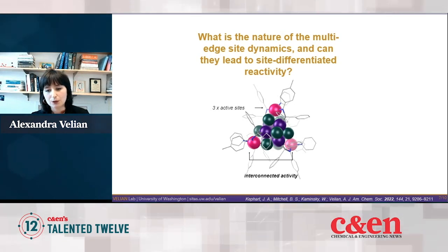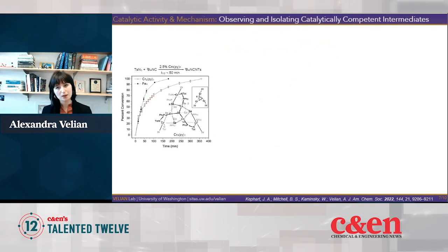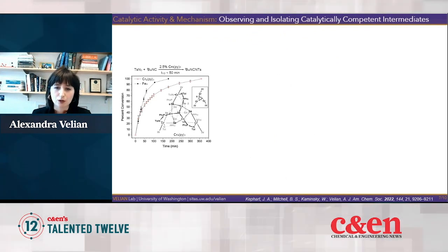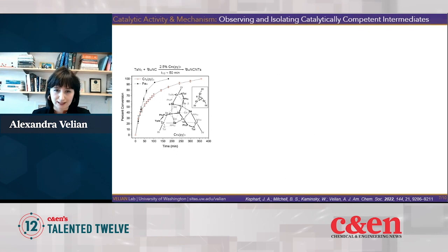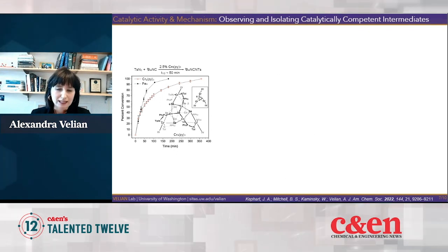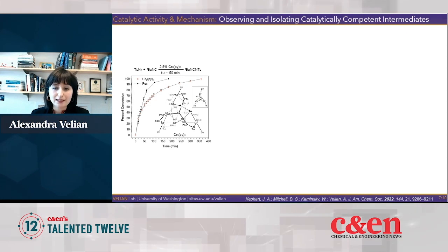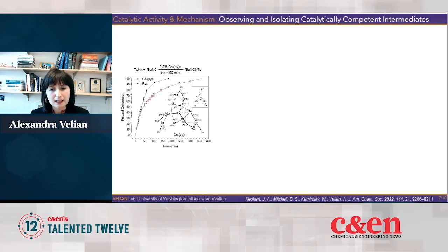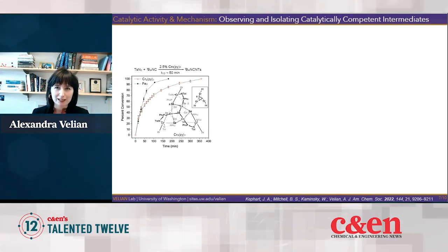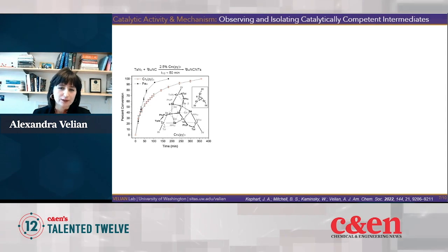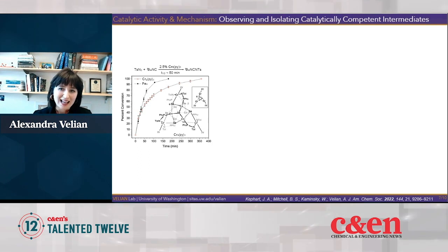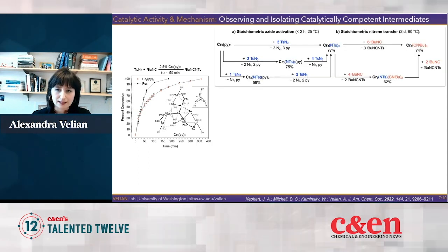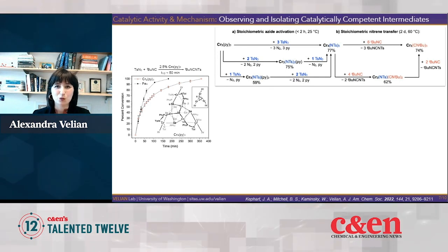And so to tell this story, I chose this trichromium cluster. Again, there's a lot of structural complexity there, but this is our nanocluster with 3 edge sites, which are chromium now. And we chose this because it provides a nice redox-independent regime between the metal and the support. And we studied in some detail a reaction that we use to benchmark our clusters, which is this azide activation and transferring of a nitrene group to form carbodiimide. These clusters are fantastic catalysts for this transformation, but what I really want to show you is that we can really gain atomistic detail into how these 3 edge sites work together